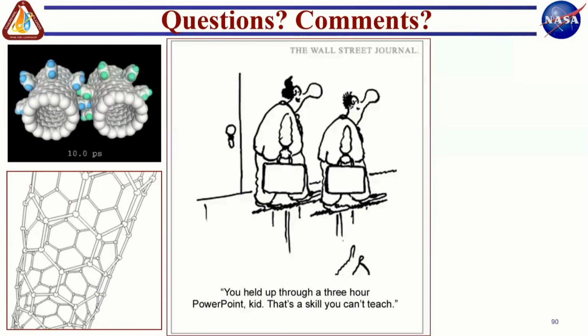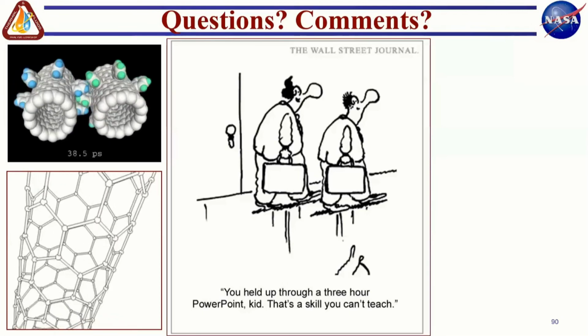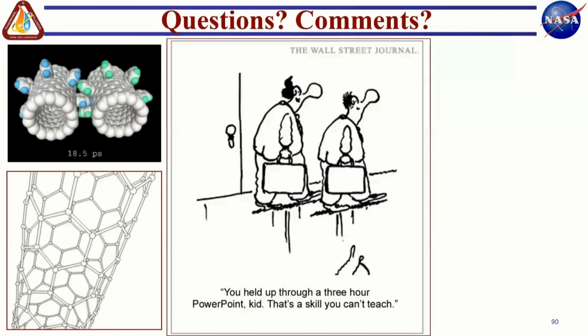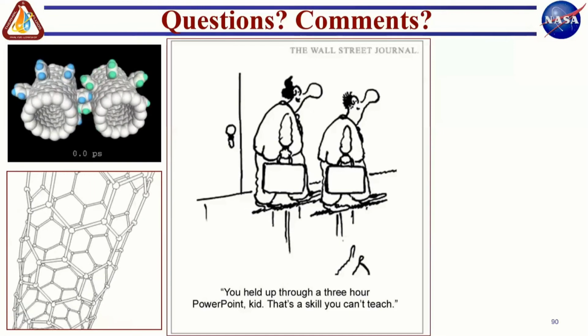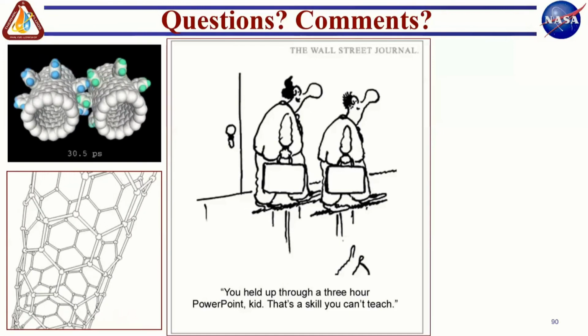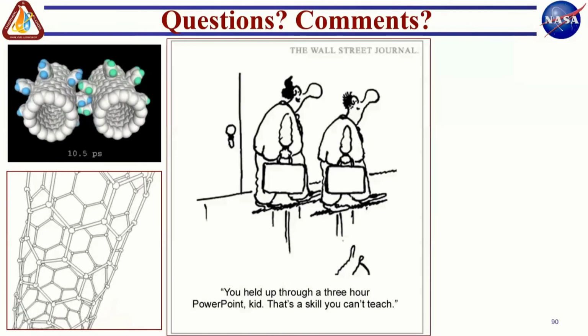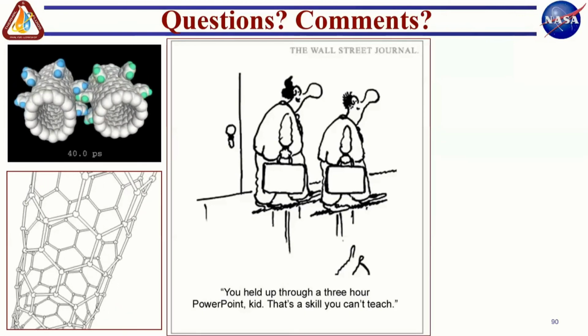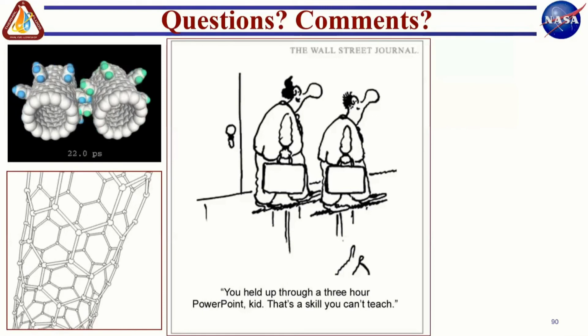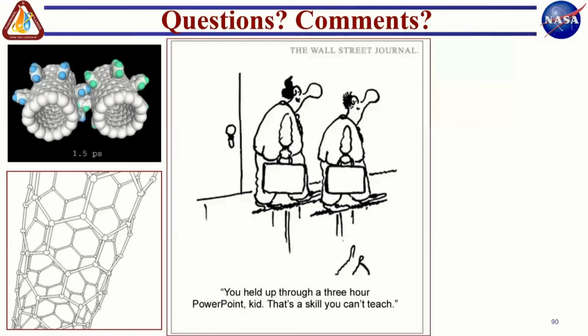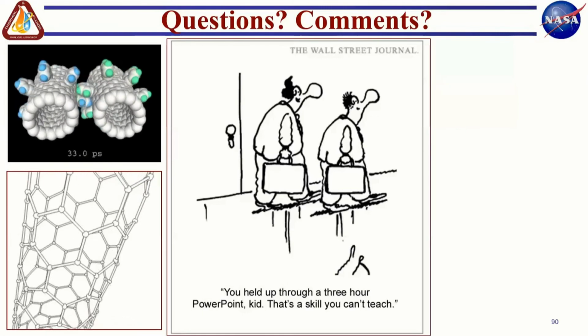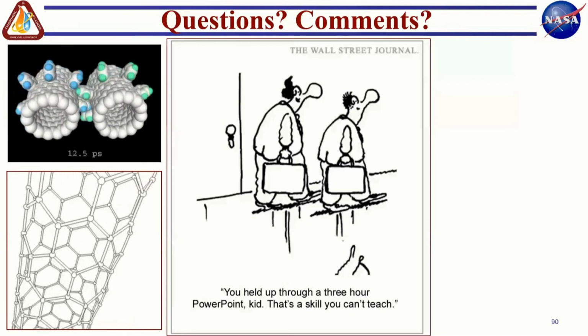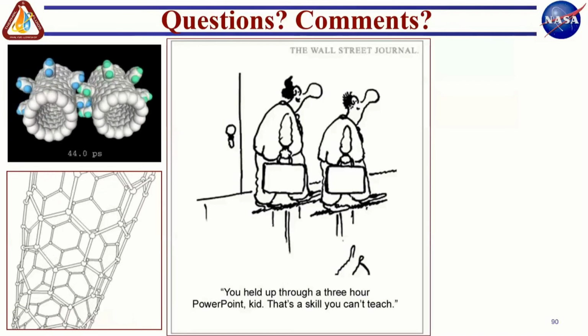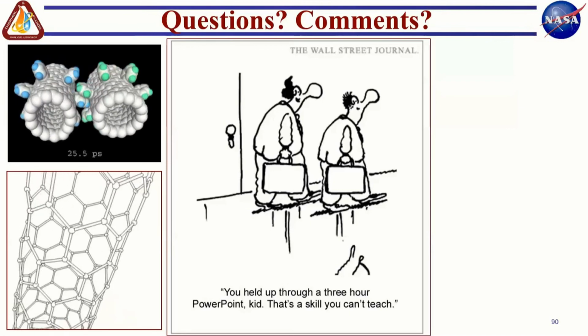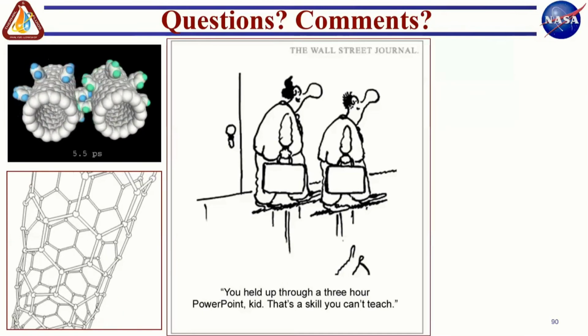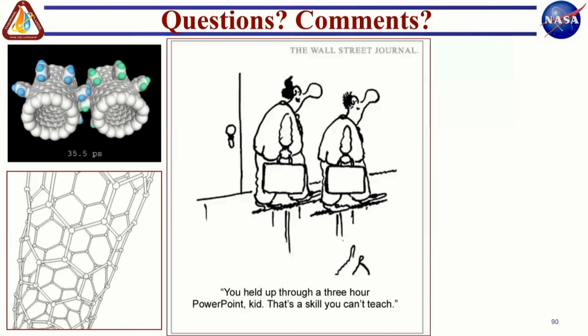Fluids, and that's also one of the fundamental insights we got from 15 years of doing nanofluids research. Fluids actually are a very important parameter in figuring out if your nanoparticle is going to be stable or not. So, for example, if it's a polar fluid like water or molten salts, you are trapping charges on the surface of the nanoparticles. So when two nanoparticles are approaching each other, they don't see each other.